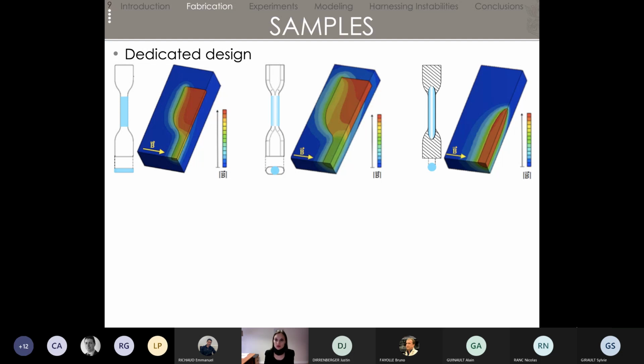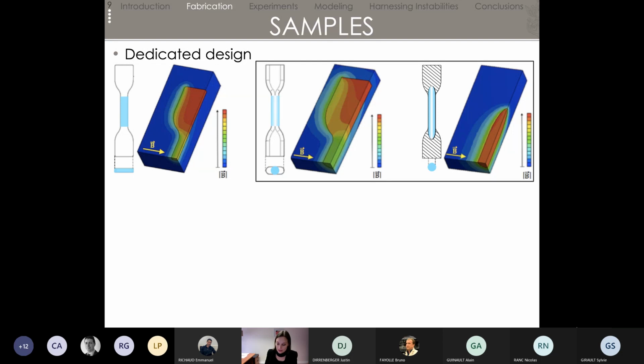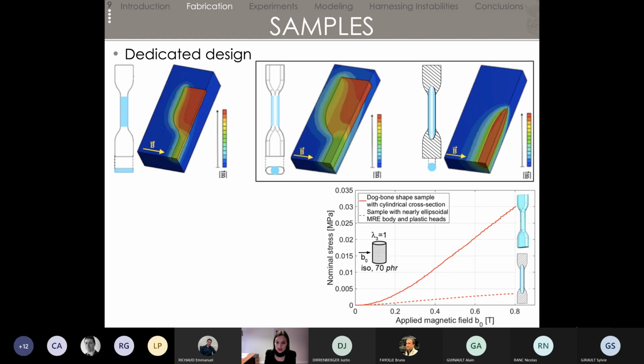So to elucidate that, we came up with a third geometry of samples. Here the body of the sample is a nearly ellipsoidal body made of magnetorheological elastomer, and the heads are just 3D printed and the two are glued together. So now on the simulation on the right, you see indeed the only magnetic part is that ellipsoidal body, and it magnetizes fairly uniformly.